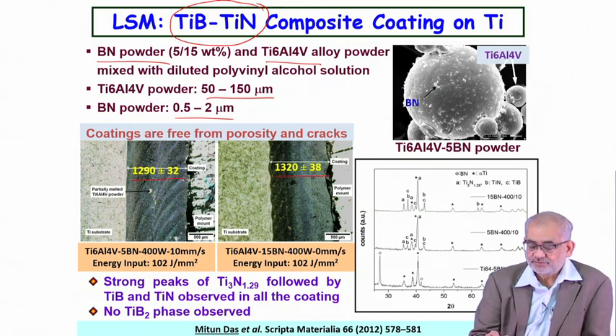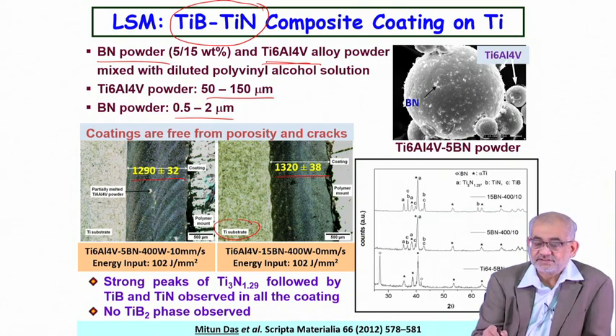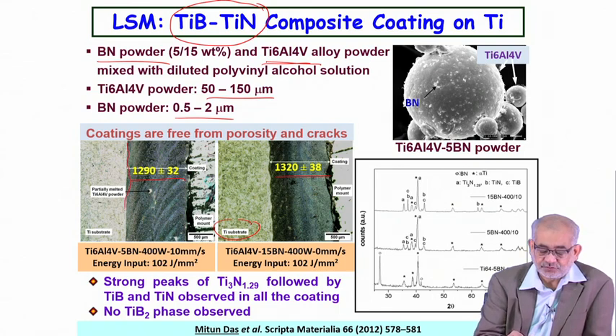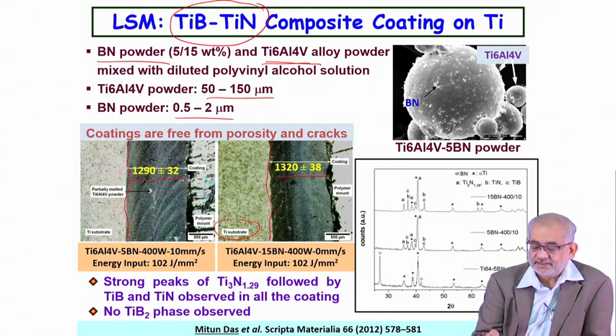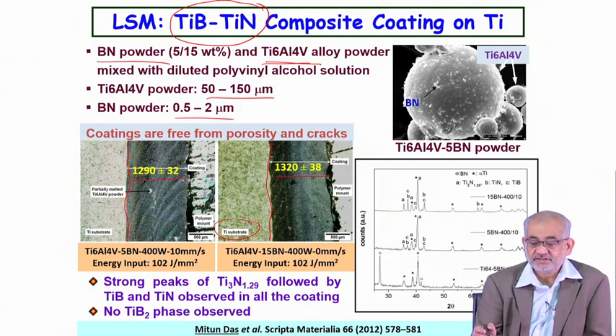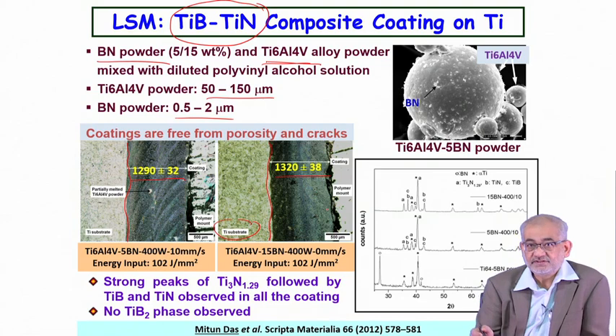But what is even more important is that the substrate is, for example, pure titanium or a titanium alloy, whose hardness on the Vickers scale would be much lower than these numbers, maybe one-third of these numbers or even less. But on top of that, you can produce a coating which is fairly adherent, because it is growing on the titanium substrate, and it is fairly thick. Compared to PVD, CVD, and other vapor-based processes, these laser-based processes can easily give you a 0.5 millimeter or close to a millimeter thick layer. It is reasonably defect-free, and most importantly, very well adherent to the substrate.